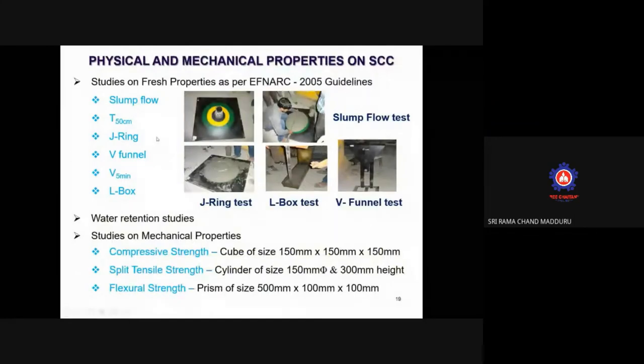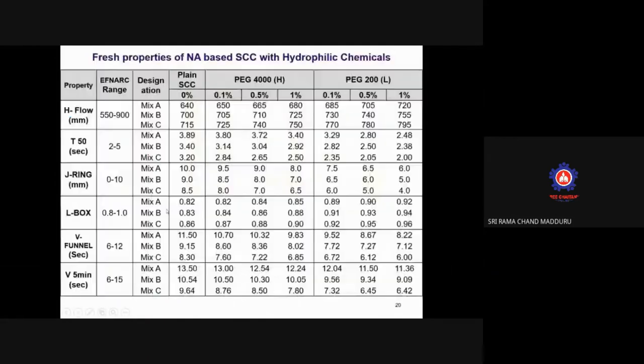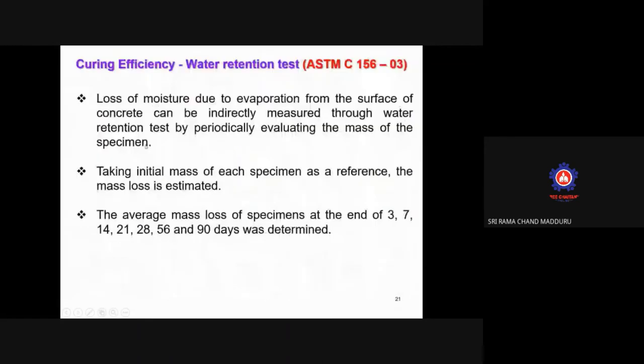And as a self-compacting concrete, it has to satisfy the water retention capacity. So here I am showing you the major basic test for self-curing concrete. As per ASTM C 156-03, to identify the curing efficiency, the water retention test is to be done. How are you doing this water retention test? Measuring the weight of the specimens.